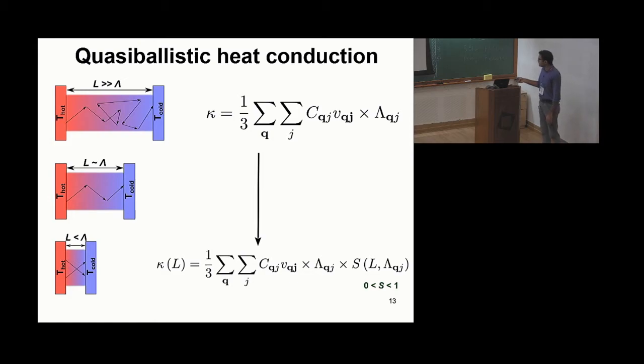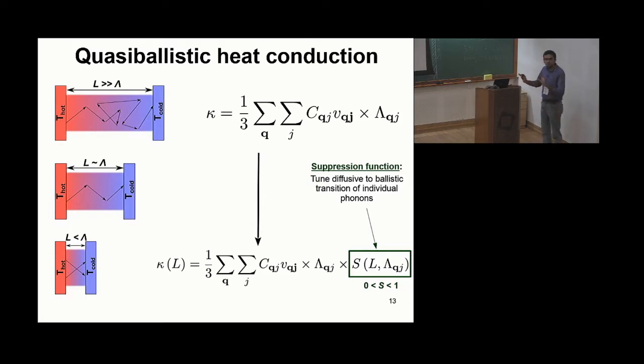This function, you can show, is bounded between 0 and 1. This is all solutions from the Boltzmann equation. And because it's between 0 and 1, any length-dependent thermal conductivity has to be smaller than the bulk thermal conductivity. So this suppression function contains the information to tune the transport property of each phonon from a diffusion regime to a ballistic regime.